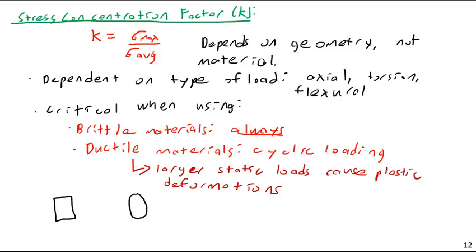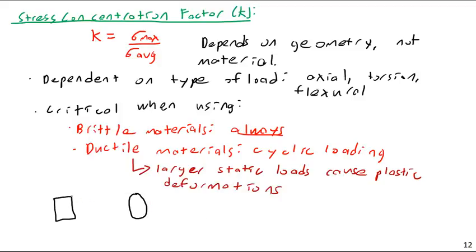And the entire reason for it is this series of plane crashes that happened back in the 50s, I believe. What they found is you had stress concentrations at the corners. Sharp corners cause stress concentration. So the plane would pressurize and depressurize, and you would get stress concentrations at your windows.